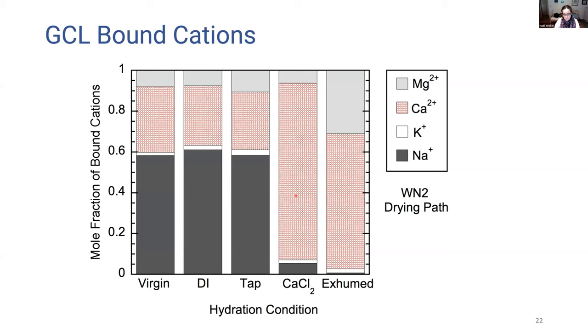In this case, exposure to the calcium chloride solution, not surprisingly, resulted in calcium being the predominant cation in the exchange complex of the clay mineral. And there's a little bit of sodium left, but not as much as the starting material. In the field, there is hardly any sodium bentonite left, and the material has changed largely for calcium and also quite a bit for magnesium as well. So we're looking at a product in these two cases that is no longer a sodium bentonite, but has switched to a calcium bentonite or a calcium magnesium bentonite.